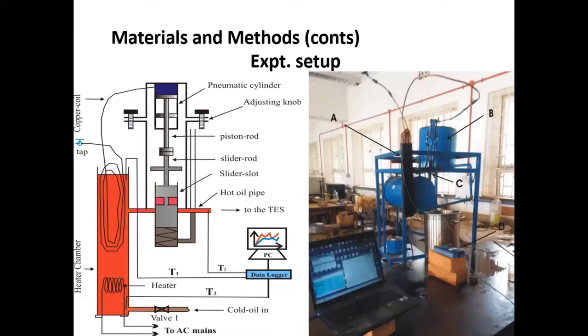When it is heated, it expands, and the plunger of the pneumatic cylinder, that is the piston rod, will extend due to the expansion. When it expands, it opens the slider valve, and when the slider valve opens at a given temperature, then this hot oil can flow to the test system. The temperatures at the top of the heating chamber, at the bottom of the heating chamber, and at the outlet of the slider valve could be recorded.